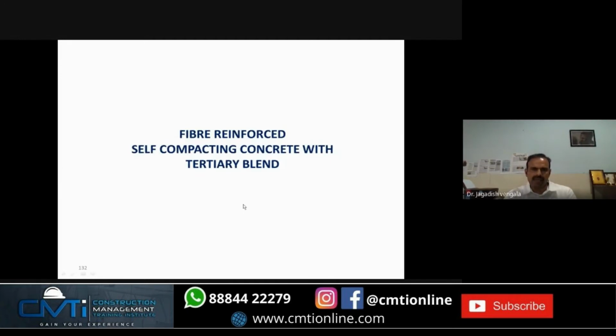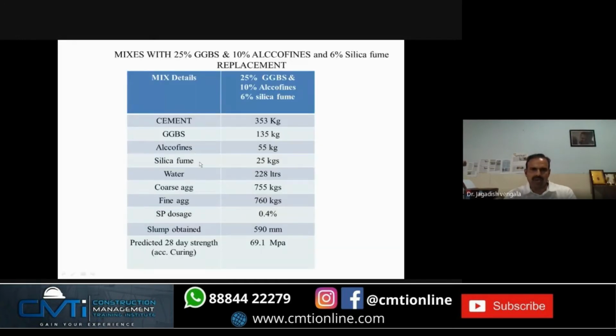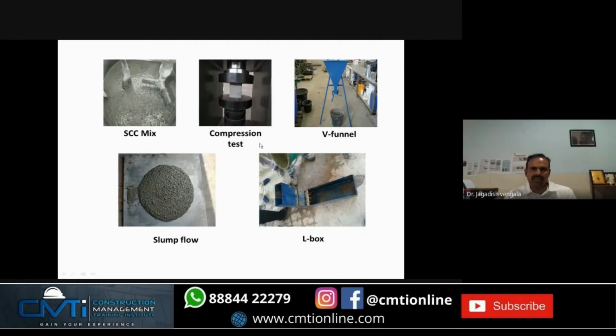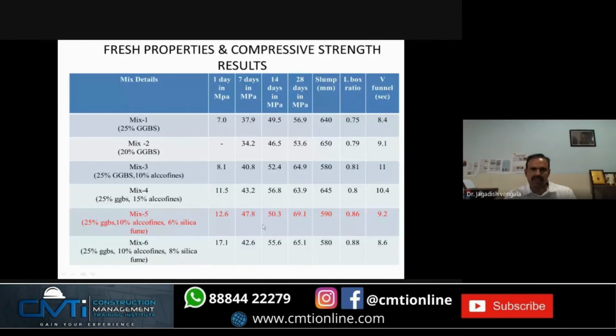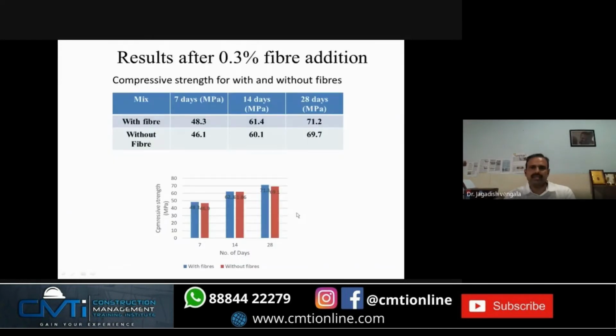And this is a tertiary blend. We tried with GGBS, alccofine, and silica fume with 350 cement and the rest of the other materials. We've conducted trials here. You can see compression test, V funnel, slump flow, L box. These are the mixes, various mixes, L box, V funnel values, slump flow values. And we added fiber too, along with the others.